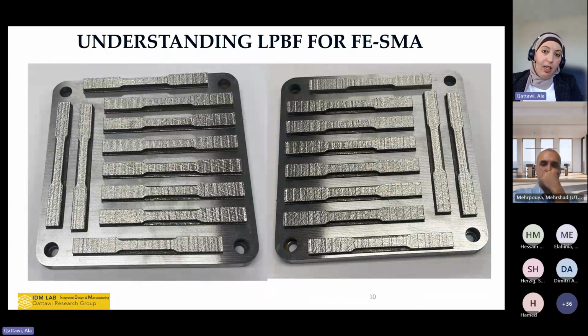Eventually, after aggregating all this data, we reached an understanding of laser powder bed fusion for iron shape memory alloy. You can see the differences in the quality of the print, like the consistency and the shiny surfaces that you can get. All that is an indication of a good print. Of course, it doesn't conclude how much porosity or micro defects you have in the samples, but it's a starting point for any additive manufacturing exploration of materials.